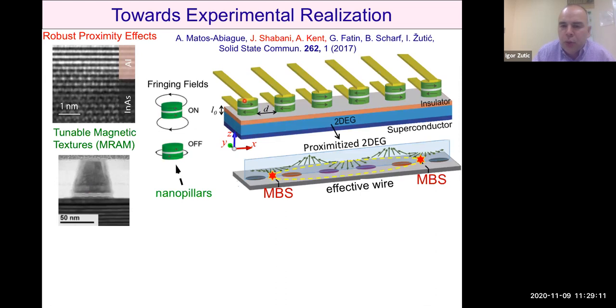So then our idea was to use again magnetic textures in 2D structures, but have a different type of array of magnets, and we can then change fringing fields from strong to weak by changing these relative orientations of magnetization. And then these fringing fields will modify the two-dimensional electron gas nearby, and therefore we will have the additional effect of the two-dimensional electron gas being modified by the superconductor. So magnetic proximity from above, superconducting proximity from below, and there may be a sweet spot where we can create an effective wire at whose ends these Majorana states would be supported.